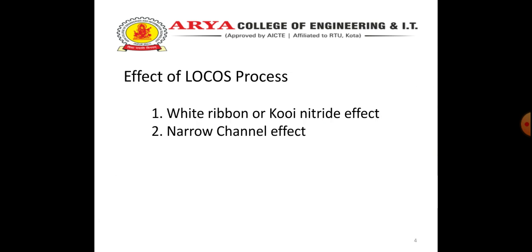The next topic is the effects of the LOCOS process. The first is the white ribbon or Kooi nitride effect. In this effect, a thermal oxynitride forms at the surface of silicon under the edges of the nitride pad. The white ribbon is caused by the reaction of Si3N4 with the high-temperature wet ambient to form NH3, which diffuses to the silicon-silicon dioxide interface where it dissociates. The surface texture caused by this nitride can be seen as a white ribbon around the edges of the active areas.